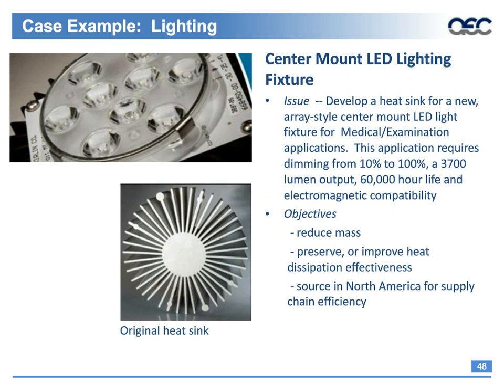Okay, here's a center-mounted LED fixture. The profile you see here in the middle, it says it's the original heatsink. So this was an offshore profile with a very solid core. This goes against some of the stuff Craig was showing earlier. You have a major mass in the middle with all these high aspect ratio fins sticking out.